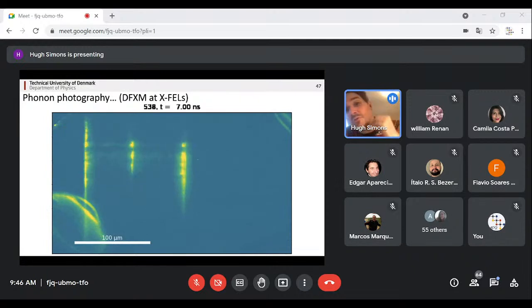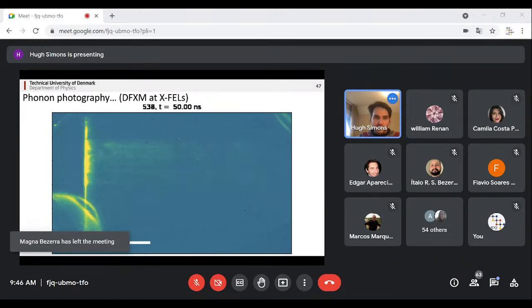But something we've been doing recently is testing how fast we can do dark field microscopy. What we thought would be the ultimate thing would, in fact, be to build a dark field microscope at an X-ray free electron laser, which rather than generating X-rays in a ring, generates them using a linear accelerator. And it does so in very fast, short pulses. These pulses are so short, they're something like tens of femtoseconds.